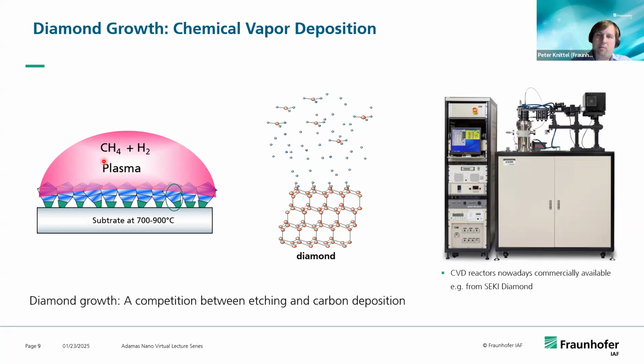The hydrogen actually is important in this approach because we are not in the conditions to grow diamond. We are at low pressures, meaning around 10 to 200, 300 millibars, so far away from natural conditions, and rather high temperatures, but not as high as it is in nature when diamonds are formed. So the stable allotrope typically in these conditions is graphite. And to avoid forming graphite from the methane or from the precursors, we have to add hydrogen that readily etches this sp2 carbon, and that leaves us only with the diamond sp3 carbon. So this is the general principle.